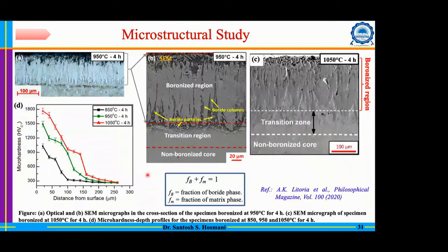So now, without delaying much, I will go to this hardness depth profile. You can see that the hardness depth profile is significantly lower for the case of 850 degrees Celsius compared to that of 1050 degrees Celsius. You may be wondering, because at both 850 and 1050 degrees Celsius we are getting iron boride, that means the compound is there, so why are the properties different?